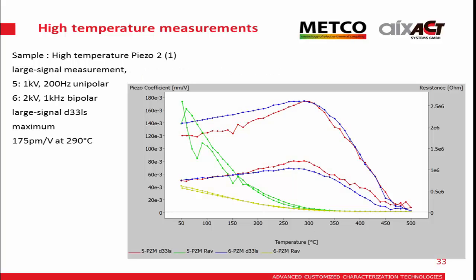And this was a similar measurement on a different material, and you can also see the behavior here. Large signal behavior of 2 different applied voltages, or bipolar and unipolar case, which show a drop earlier. And the resistivity is plotted here, going from mega ohm range to a few kilo ohms. This is also a challenge. So you need a really big amplifier if you would like to drive the samples up, or very tiny pieces.